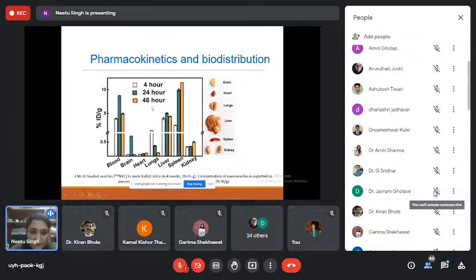Okay, so this is exactly what we looked at. We looked at the organs and we looked at how much is present. You can see that after 24 hours, it was still present in the blood. It started to drop after 24 hours. And in the blood after 48 hours, about 5% was present.